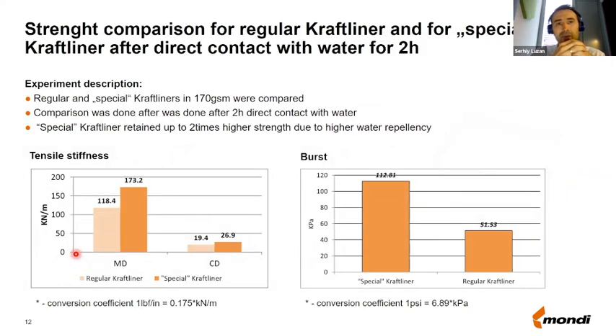Here you have an example of two different types of kraft liners. One I call a regular kraft liner, which was produced without this special treatment with a size press on the surface, and another, which I call the special kraft liner, where special water repellent polymers were put on the surface. These two types of paper are compared after the surface of paper was subjected for 2 hours in direct contact with water. After 2 hours, we tested the tensile stiffness of paper. So basically we stretched the paper until it broke. And we also tested the burst properties of paper.